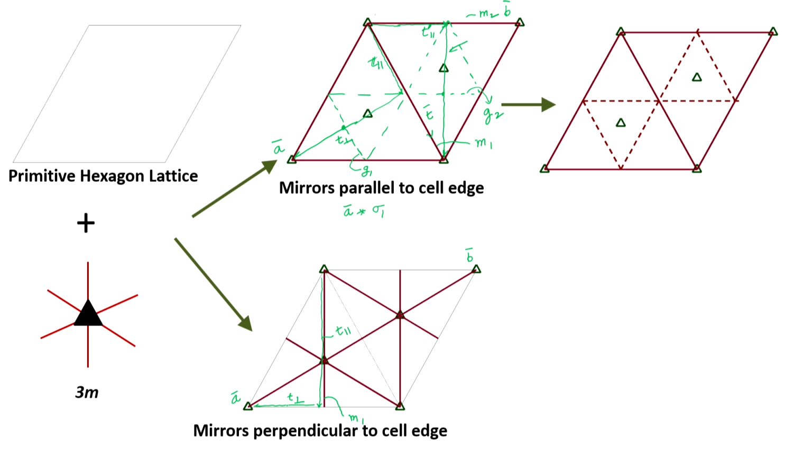Very clearly, I do not need to do anything more. The glide plane should appear at the midpoint of this perpendicular component and parallel to the mirror M1, which means that this is how this mirror would be. Now, is T parallel exactly half the translation vector in the particular direction or not? Let us look at this diagram.